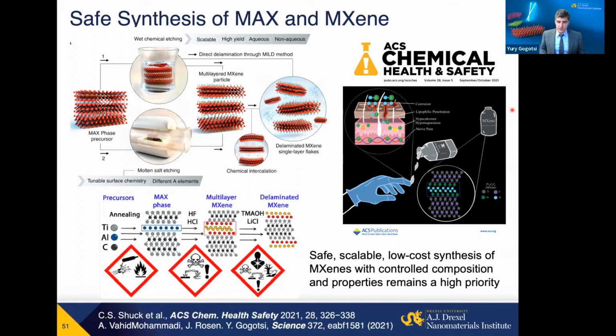One, you can use them in membranes for separating organic molecules and ions, letting water go through because they're hydrophilic, and you can potentially control spacing between the layers. MXenes have been shown to be very good sorbents for heavy ions like lead, uranium, chromium, and others, so they can be used to remove those toxic heavy ions. And again, they have catalytic and photocatalytic properties because of their plasmonic properties in the visible or IR range, and can be used to catalytically destroy organic molecules. So this is another potential application here.